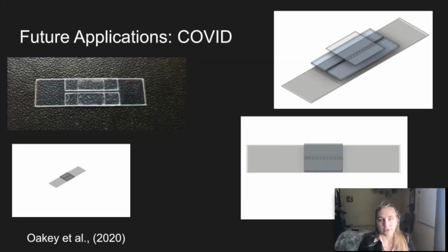A final application of microfluidic devices is both COVID-19 research and COVID-19 rapid testing. In our lab, we are developing a prototype of microfluidic devices made out of PET to be used for COVID-19 rapid testing as another way to test for the viral proteins in the saliva. These PET devices are made from the Epilogue laser printer in the makerspace here on campus, where small pieces of PET and the adhesive are cut from the laser, and then chambers of the device can be made by sticking